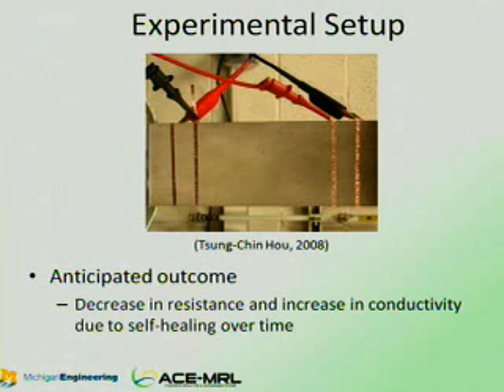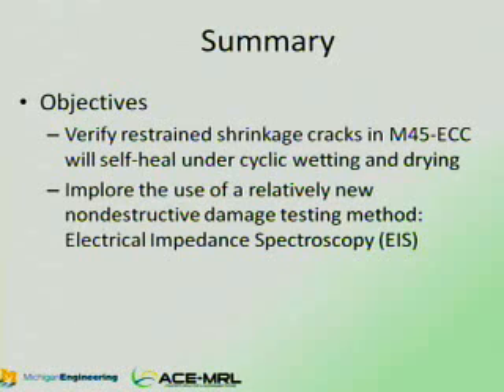The outer two copper strips will pass the current, while the inner two strips will pick up the impedance across the specimen. I anticipate that the resistance will decrease over time due to self-healing, and the conductivity will increase due to the healing of the cracks. In conclusion, my research will verify that restrained shrinkage cracks in M45-ECC will self-heal under cyclic wetting and drying. I will also explore the use of a relatively new non-destructive damage testing method, which is EIS.